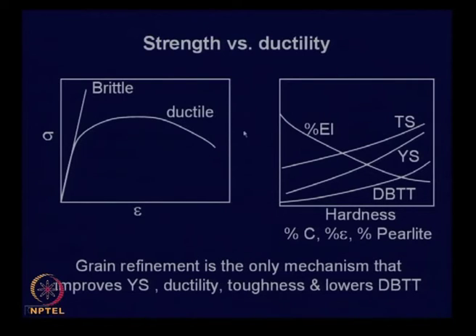Now, most of the strengthening mechanisms adversely affect ductility, toughness and the ductile to brittle transition temperature. There is one mechanism, which is grain refinement. This is the only mechanism that improves yield strength and at the same time does not adversely affect ductility or toughness, and in some cases it is reported to have lowered the ductile to brittle transition temperature.